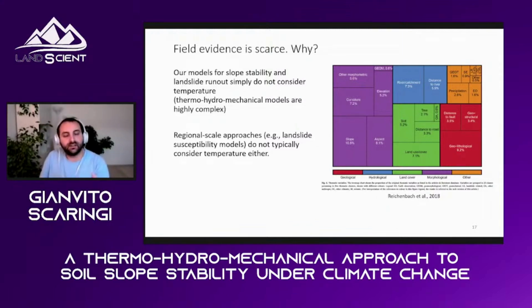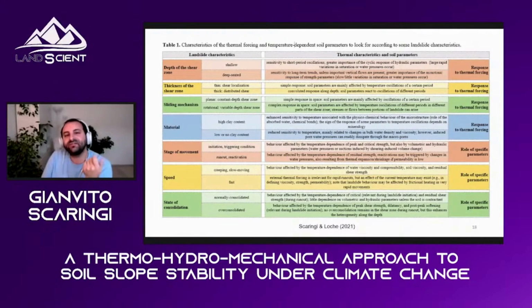Before I move to that, this was one reason. The models do not include temperature. The second reason why there is not much field evidence is because the field is not as simple as the laboratory. In the laboratory, samples are homogeneous, are simple, you control the condition. But in the field, you have different lithologies, in fact, different types of landslides, and so different thermal effects. For example, this table that comes from our paper in Geomorphology shows the possible effects of temperature depending on the depth of the shear zone. So shallow versus deep-seated landslide, thermal effects are different.